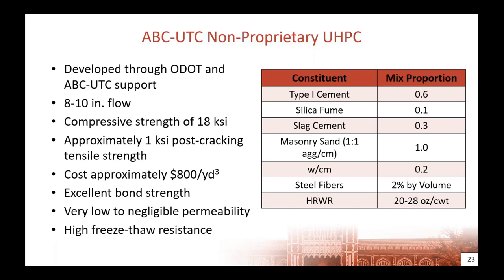We've tested this extensively, achieved a compressive strength of about 18,000 PSI consistently, about 1 KSI post-cracking tensile strength, and a cost of about $800 per cubic yard. We've seen excellent bond strength, seen that low to negligible permeability and high freeze-thaw resistance.